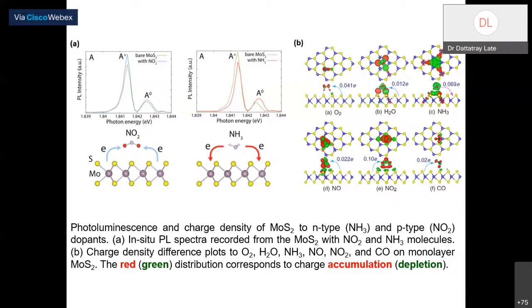When you talk about the molecular level, you can also see the photoluminescence and charge density of MoS2, because ammonia is N type and NO2 is P type, right? In particular in figure B, we see the charge density difference plots of oxygen, water molecules, ammonia, NO, NO2 and CO on the monolayer. The red which I have shown here corresponds to charge accumulation, and the green is the charge depletion. These are the origin of the sensing mechanism on the surface of the MoS2.